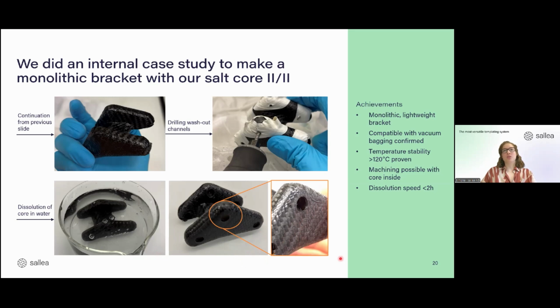We also learned, or knew, that our salt cores are compatible with vacuum bagging. Also, that it's temperature stable beyond 120 degrees was proven, and that machining is still possible when the core is still inside. And I think one of the most important things is that it still dissolves quite quickly, in this case still below 2 hours.